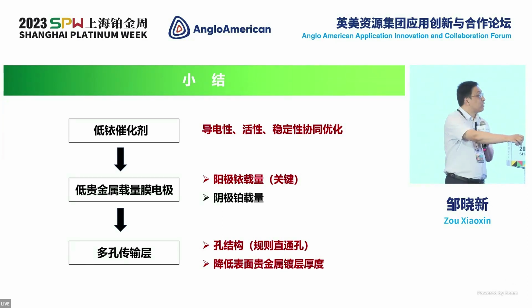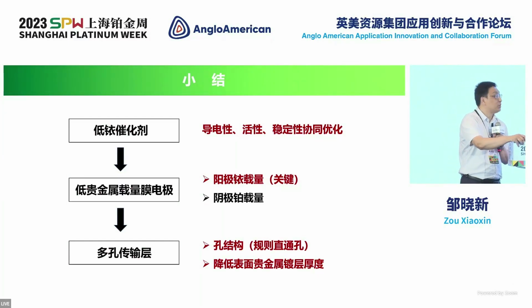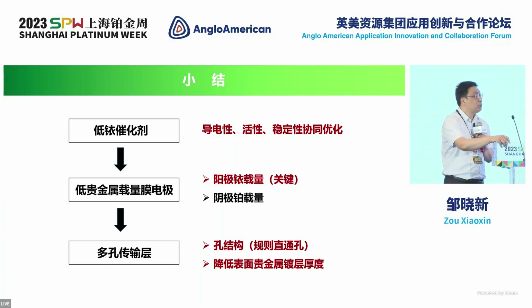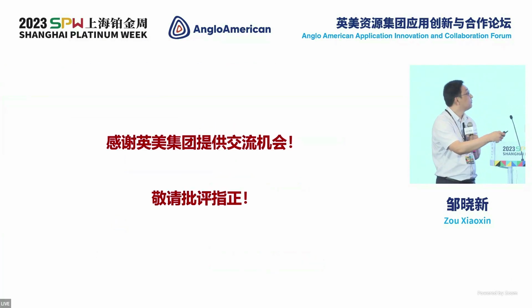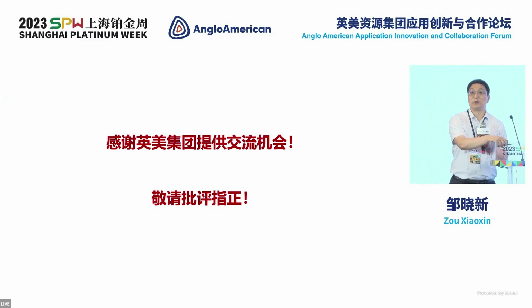In terms of the transport layer, personally speaking, in terms of the porous structure, we have the irregular structure formed by carbon felt, and we have seen the transition towards the straight-through pore structure. So that shows optimization. And also we need to reduce the thickness of the surface coating layer, the precious metal coating layer. In the future, there might be technology to reduce the coating layer as well.